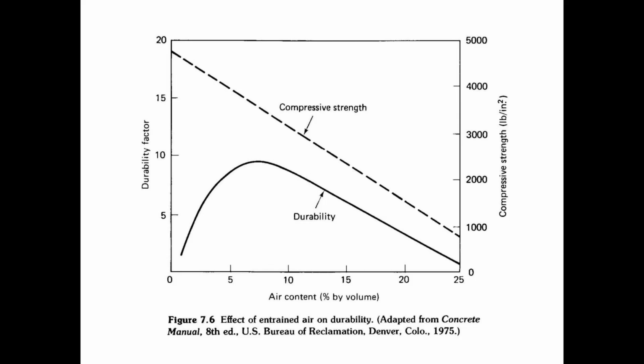So instead of using an air content of 4 to 10, I'm going to say my target air content is 4 to 7. So that way I'm getting the same level of durability that I would with an air content range of 4 to 10, but I'm getting better strength on average than I would if I was using an air content of 4 to 10.